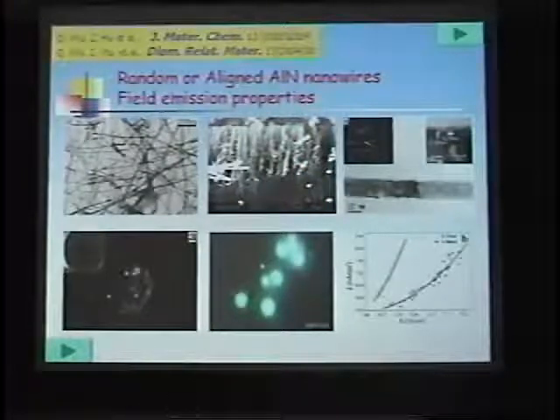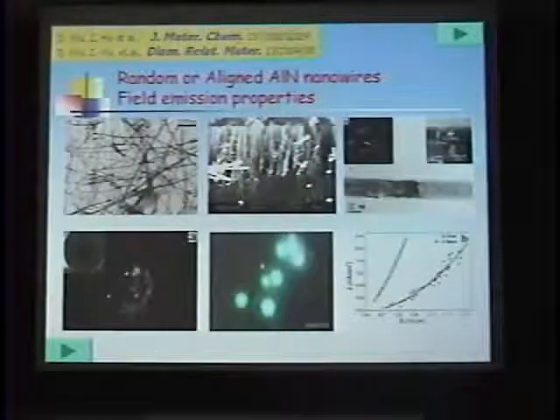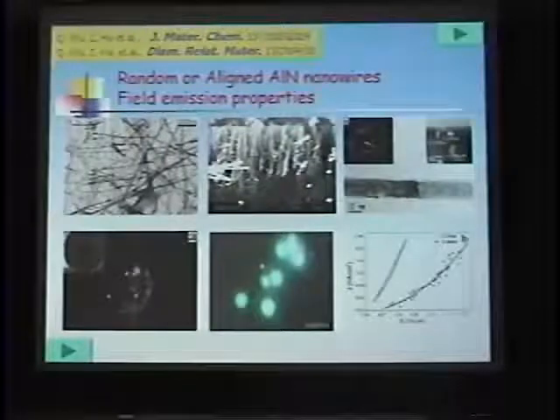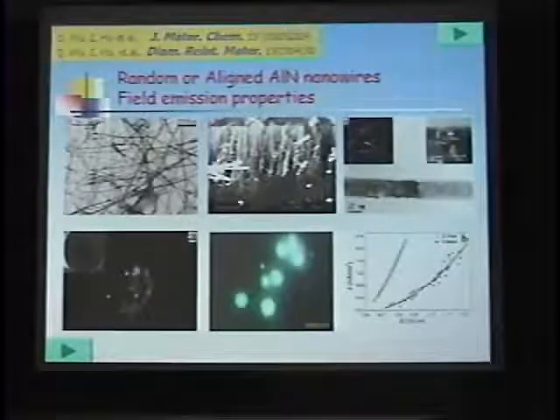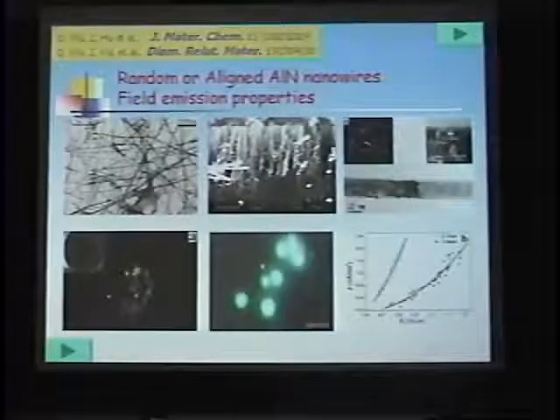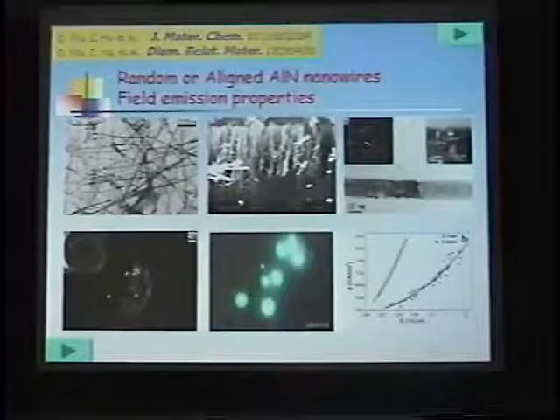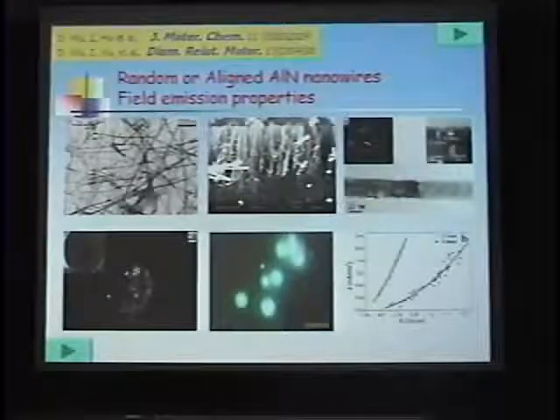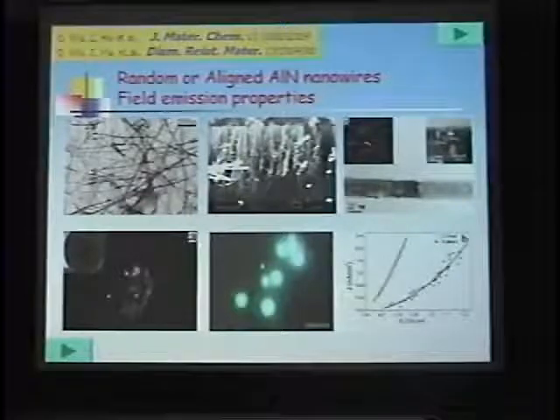As we know, the one-dimensional nanostructure is helpful for enhancing the field emission effect. And also, aluminum nitride has a very small or even negative electron affinity. So both these effects are favorable for field emission. So maybe aluminum nitride is a promising field emission material.